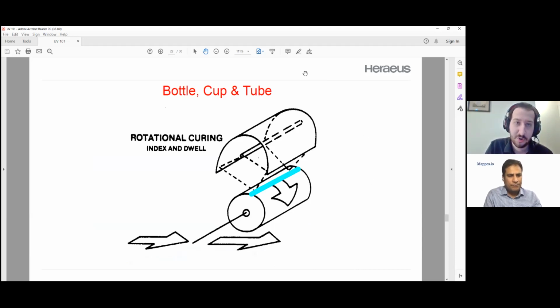Actually, this one here is showing an example of a rotating bottle or tube part. So you can actually cure the outside of a bottle. You print a label onto the side of a bottle. You would have to rotate the bottle in order to dry the entire label on the outside of the bottle. So by having a static lamp and a rotating part, you can rotate the bottle around at a pretty high speed and dry the entire label in a rotational curing process.